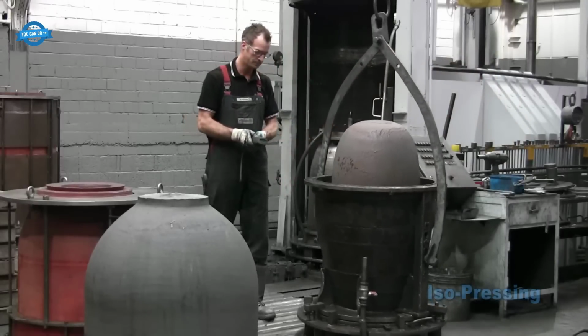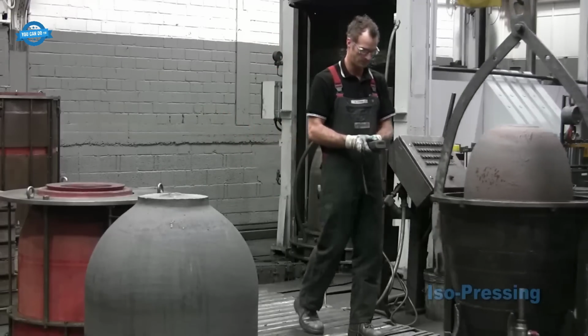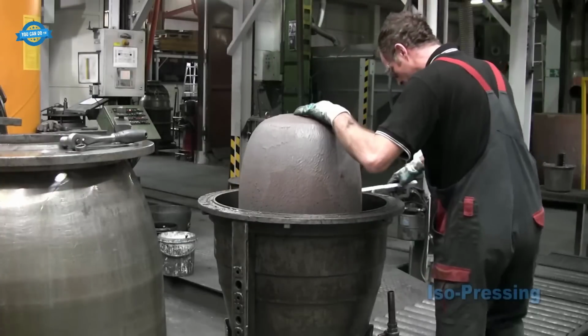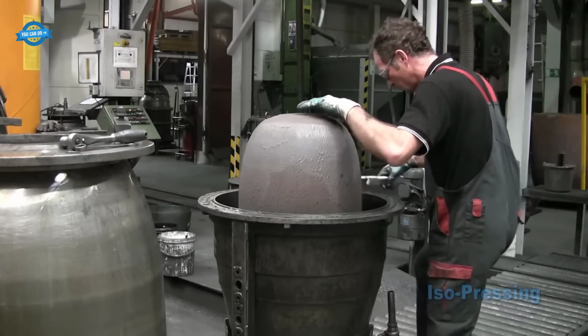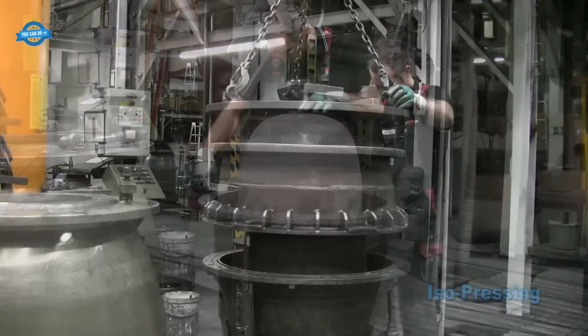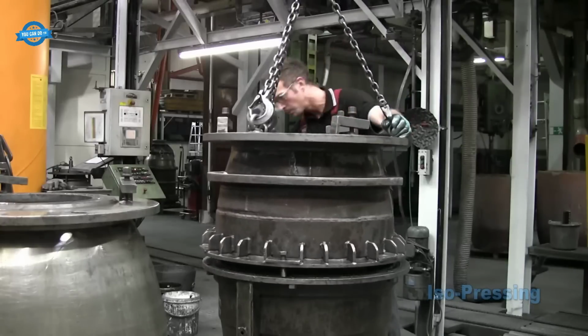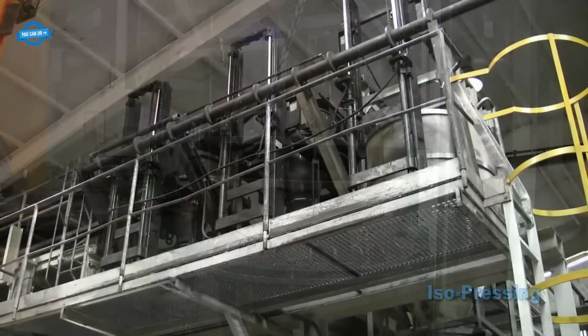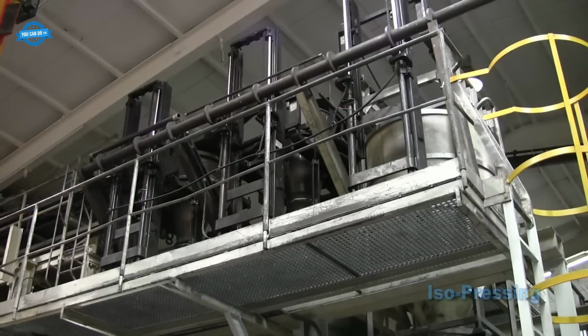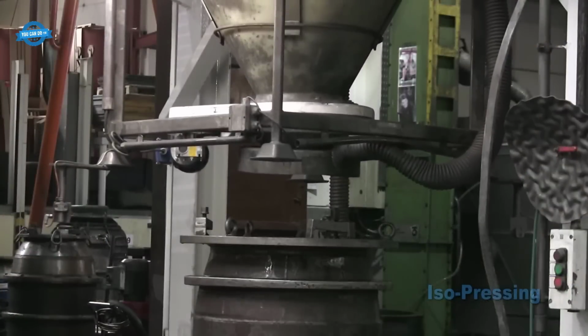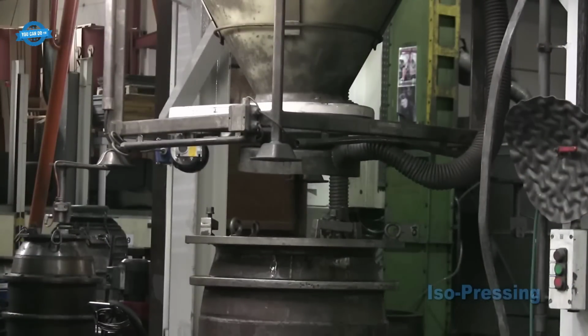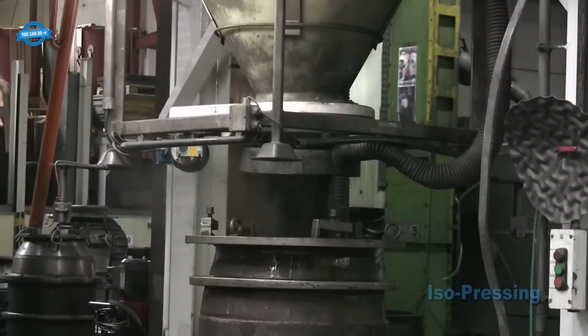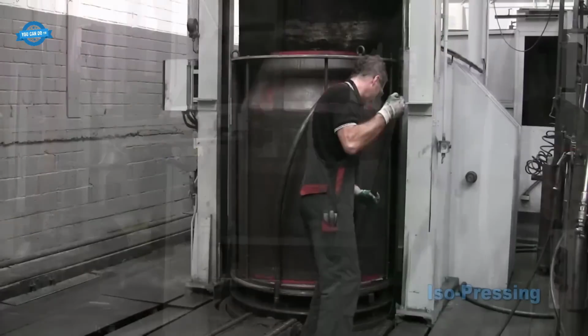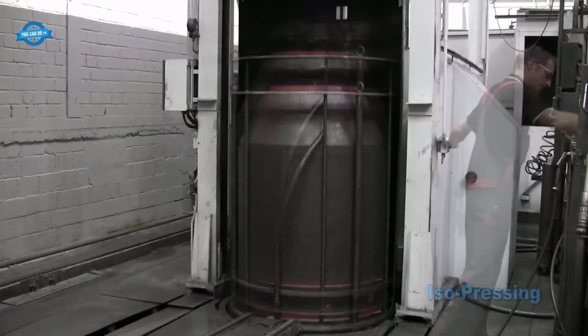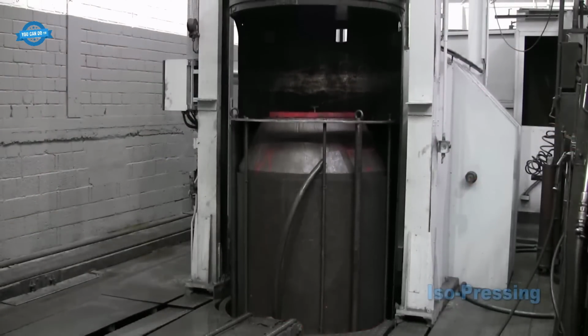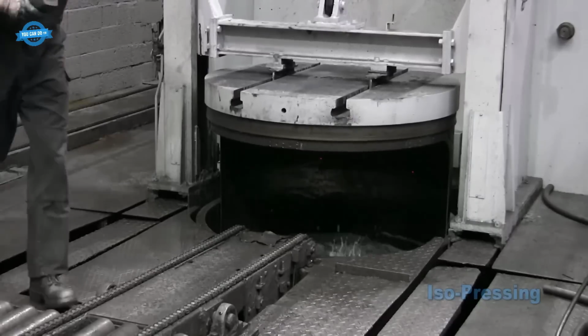The air and overhead material dispensing system are employed to fill the mold with clay graphite or silicon carbide material tailored to the specific crucible being crafted. Once the mold reaches the isopress, it is loaded onto a lift that lowers it into the pressing chamber filled with water. The isopressing cycle commences with an increase in pressure via oil pumps until the maximum pressure is achieved. Following a brief holding period at the maximum pressure, a programmed decompression process begins. This series of fixed steps results in the removal of all pressure.